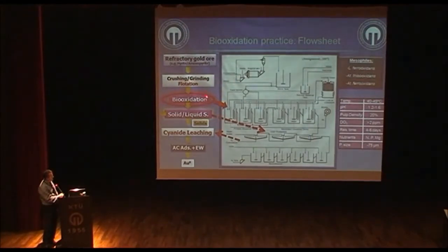At this stage, because chemical pretreatment methods incur a cost, to reduce the cost, the bulk of the material can be reduced by flotation, or gold can be selectively recovered. Then the bio-oxidation is applied, and after the oxidation of the sulfide, the gold remains in the solids, and after solid separation, the solid fraction is sent to cyanide leaching.